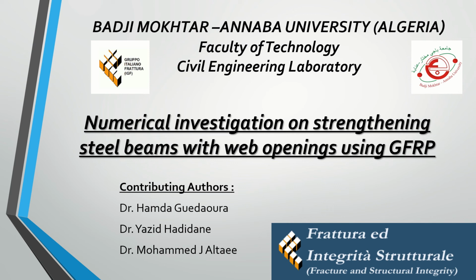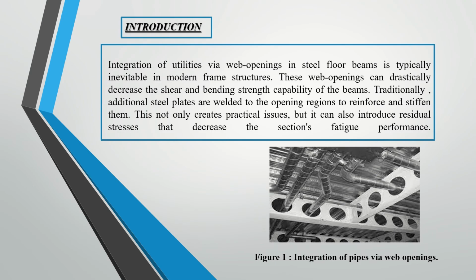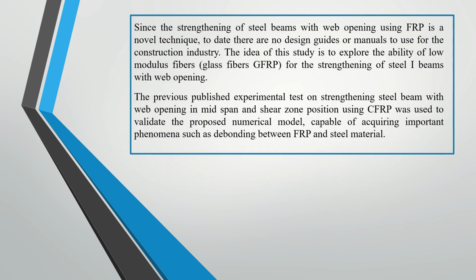Our contribution is entitled Numerical Investigation on Strengthening Steel Beams with Web Openings using GFRP. Integration of utilities via web openings in steel floor beams is typically inevitable in modern frame structures. Traditionally, additional steel plates are welded to the opening regions to reinforce and stiffen them. This not only creates practical issues, but can also introduce residual stresses.